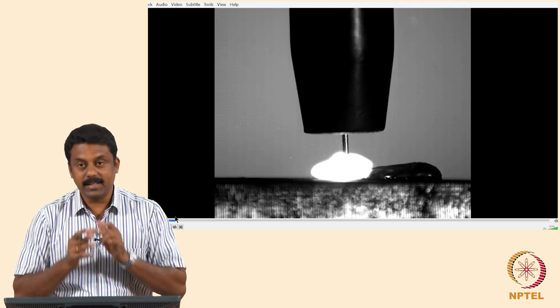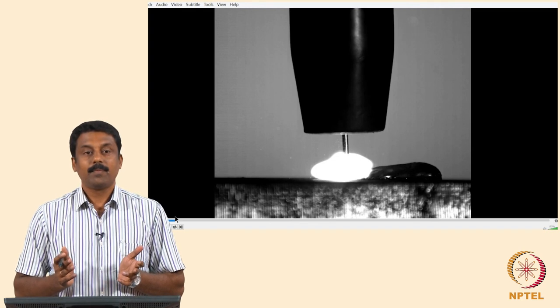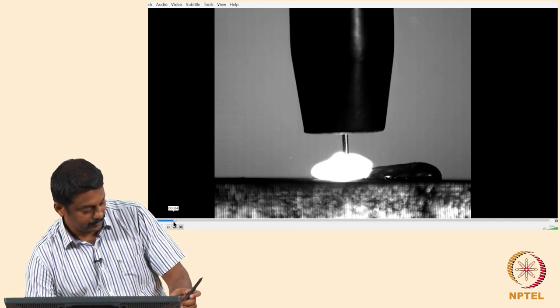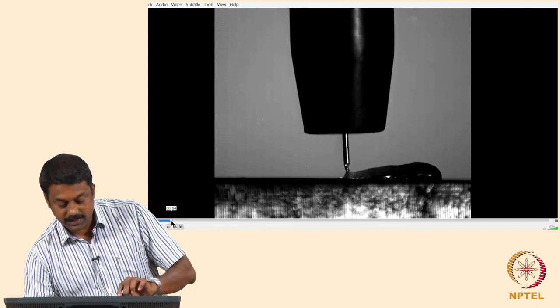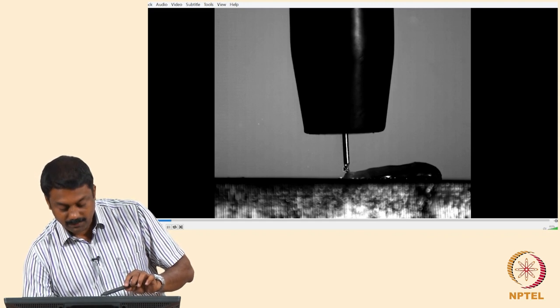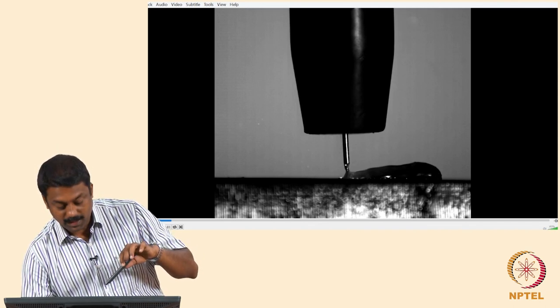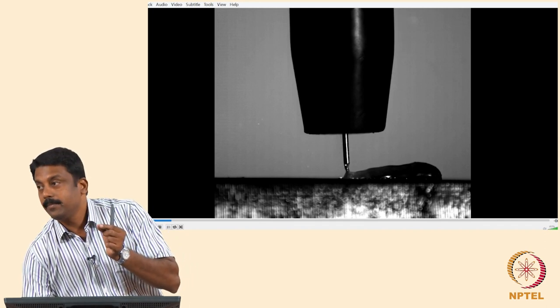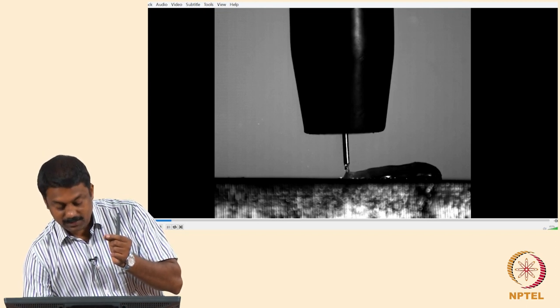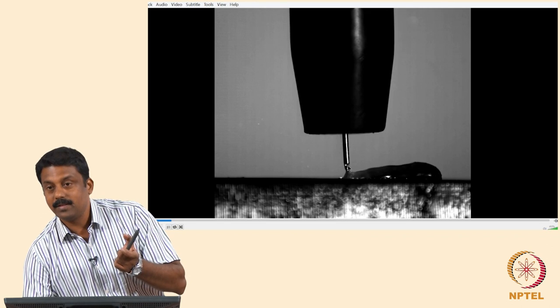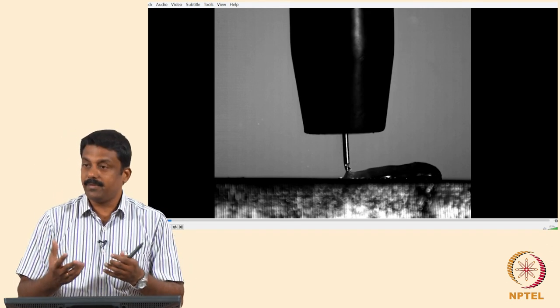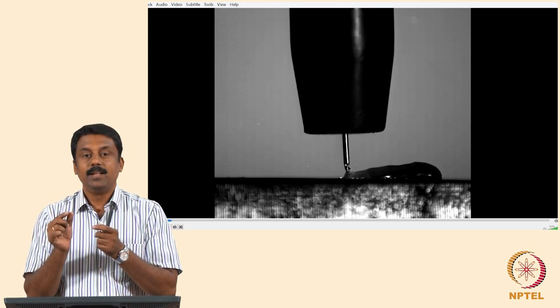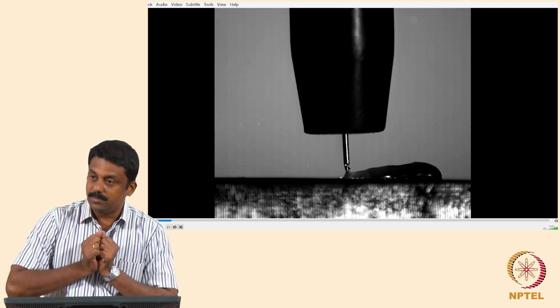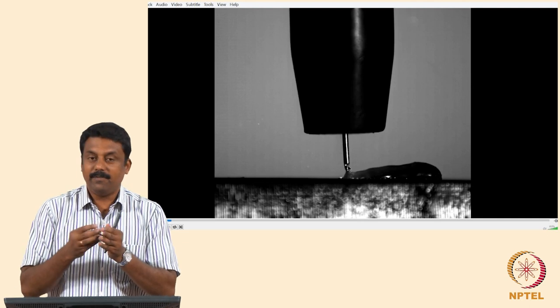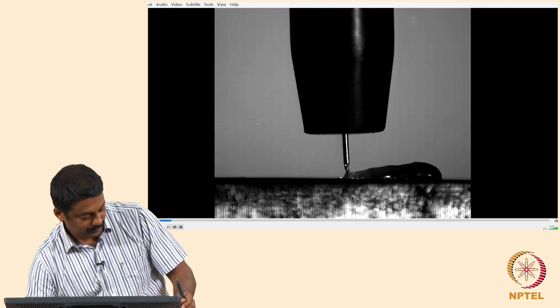Okay. So what happens if you keep on passing the current? Then you will have an explosion. If the current is passed continuously, suppose an equal amount of current is passed like an arcing current, and you have a very small area neck forming when you are retracting or doing a short circuiting, and you have an enormous amount of Lorentz force concentrating on a very tiny neck. So if the Lorentz force is concentrating on a tiny neck, obviously it will cause an explosion, right? Because if you keep the current constant, the amount of Lorentz force is confined to a very tiny area. And the moment you constrain the Lorentz force, you have an explosion, because the electrons are concentrating now on a very small neck. So that is the reason.